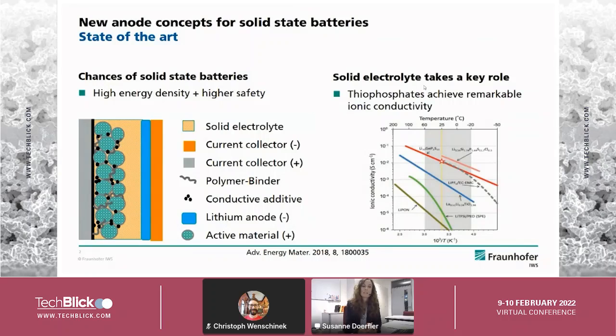On the left-hand side, we can see a scheme of how such a solid-state lithium-ion battery could look. We have an NMC cathode laminated on a current collector with conductive additive, and a current collector on the anode side. As the active material on the anode side, we need to employ a thin-film, high volumetric capacity anode, because otherwise we don't gain much in watt hours per liter. If we just use a lithium-ion battery with a graphitic anode and swap the liquid electrolyte for a solid electrolyte, then we don't gain in watt hours per liter, and we actually lose in watt hours per kg.